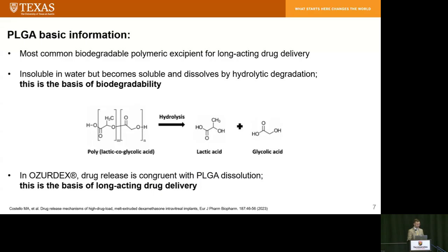The linkage between the monomer units in the polymer is hydrolyzed, which ultimately leads to reducing the polymer to the monomers themselves, lactic acid and glycolic acid. And those are naturally present in the body, so that's the biodegradability aspect. In Ozurdex, drug release is congruent with that PLGA dissolution process. This is the basis of the long-acting aspect of drug delivery because the PLGA dissolution process takes a long time.